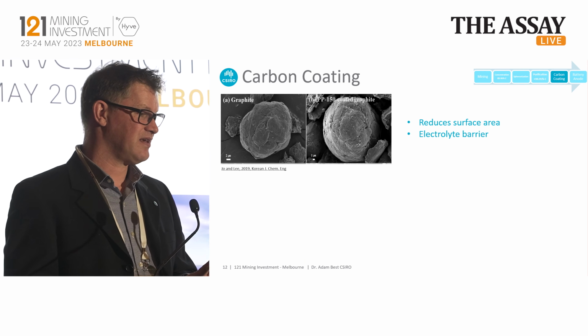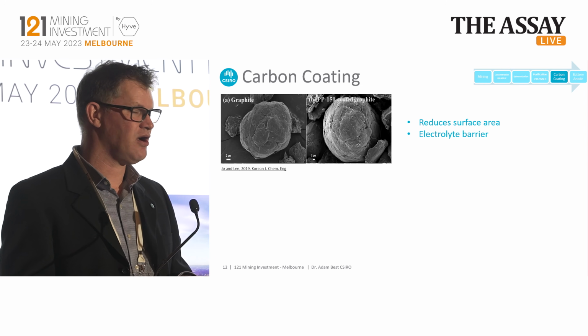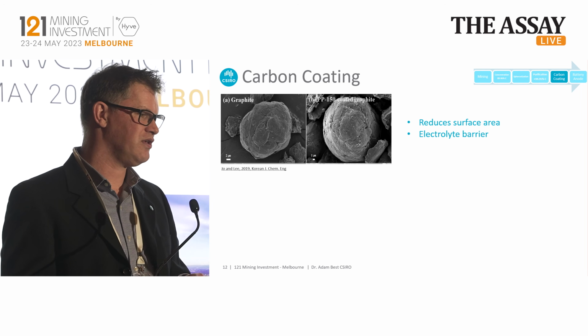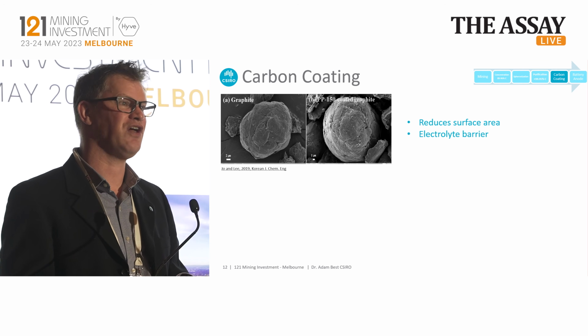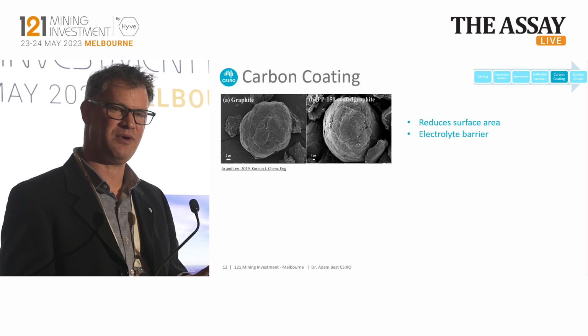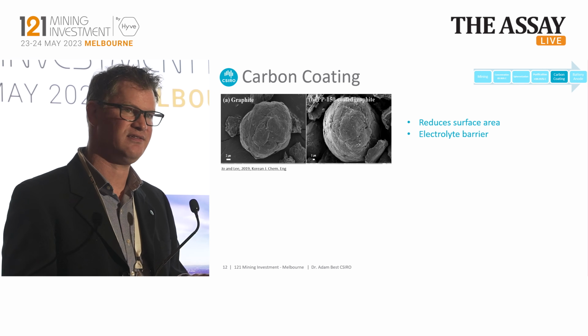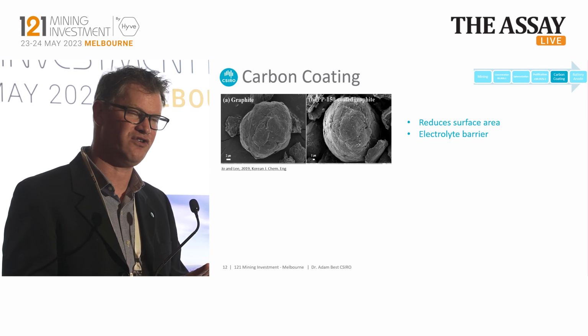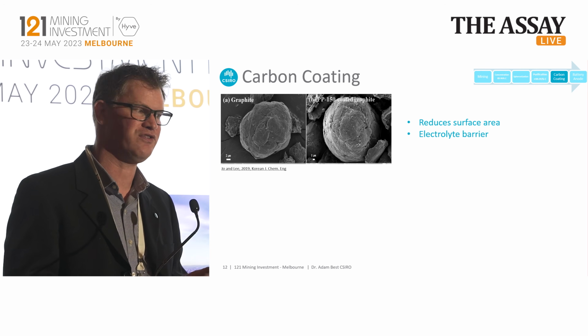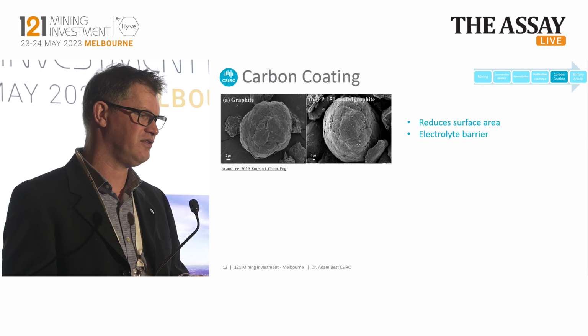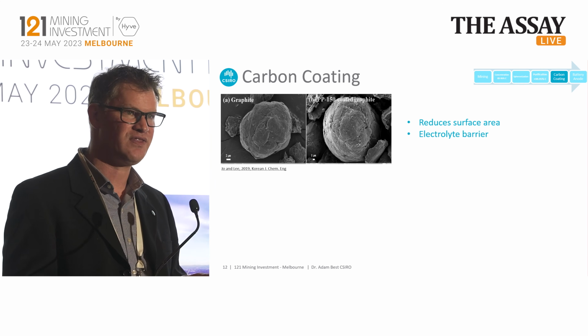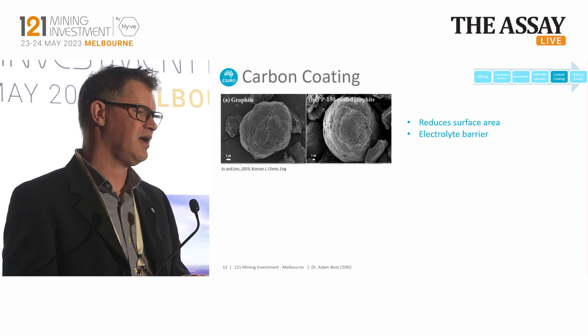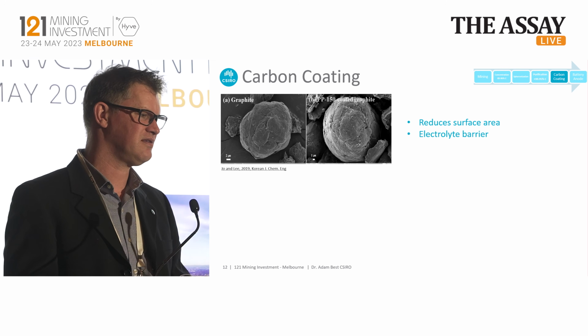The last step is carbon coating. So now you've got a 99.99% graphite, and what you're now trying to do is to reduce the surface area further. So earlier I spoke to you about solid electrolyte interphases and that surface chemistry and those surface reactions. We want to remove those as much as possible. So what we're now trying to do is to reduce the surface area further, to get it as low as possible, while maintaining the same particle size, so we can get the best electrochemical performance.